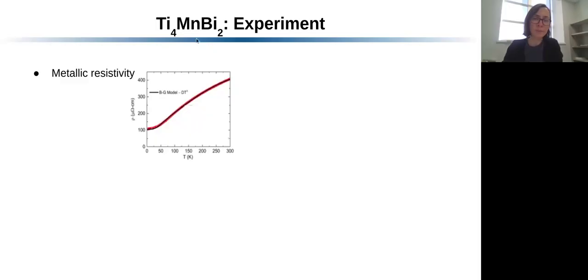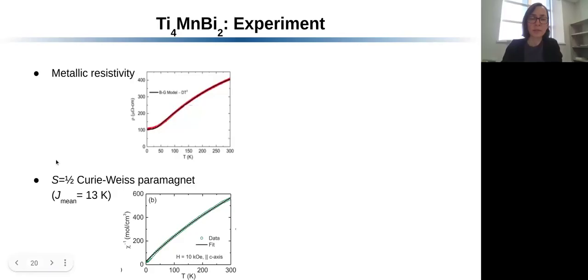Now, as many intermetallic systems, this system is a metal, as you can see here, which is probably the only kind of normal property of the system, because when you measure its magnetic properties, you find that it behaves as a paramagnet with a magnetic moment that corresponds to spin 1/2. And this is something that you do not expect to see in a system containing manganese atoms, because manganese atoms or ions almost always are in a high spin magnetic configuration, which is spin 5/2. So that was a real puzzle to see this behavior in the system containing manganese.